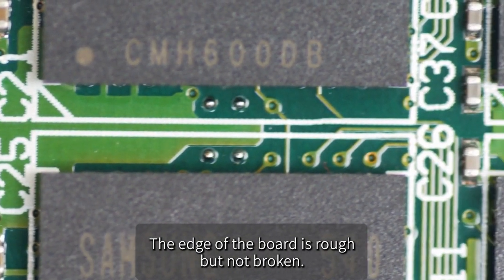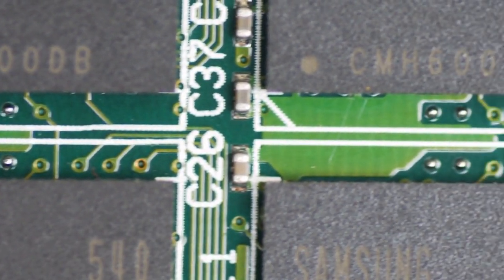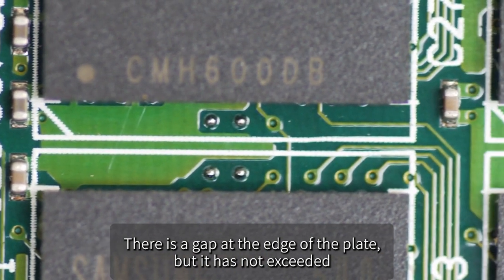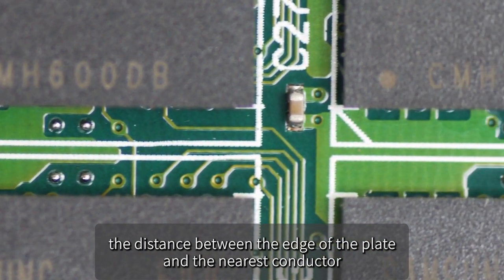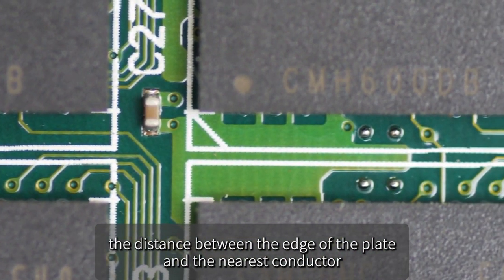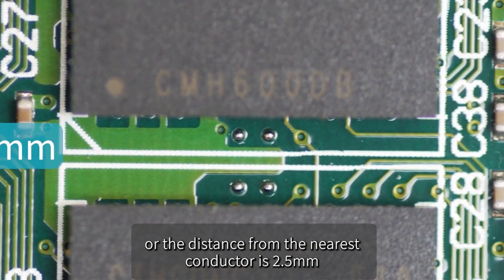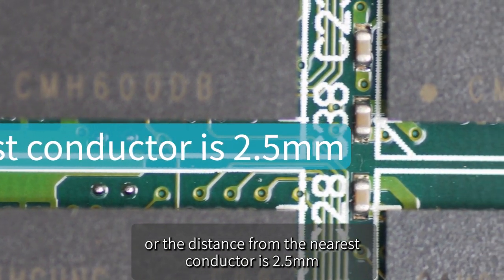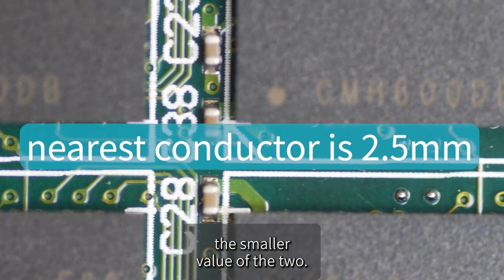Edge notch. The edge of the board is rough, but not broken. There is a gap at the edge of the plate, but it has not exceeded the distance between the edge of the plate and the nearest conductor, or the distance from the nearest conductor is 2.5 mm, the smaller value of the two.